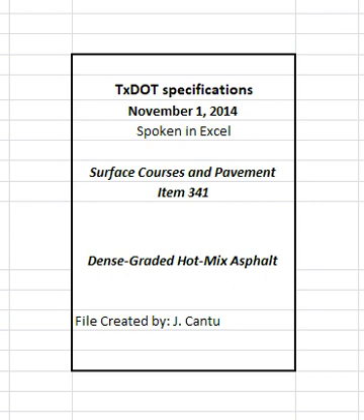4.9.2.4.2 Asphalt binder content. A sublot is defined as out of operational tolerance if either the engineer's or the contractor's test results exceed the values listed in Table 11. No production or placement payment adjustments greater than 1.000 will be paid for any sublot that is out of operational tolerance for asphalt binder content. Suspend production and shipment of the mixture if the engineer's or the contractor's asphalt binder content deviates from the current JMF by more than 0.5% for any sublot.